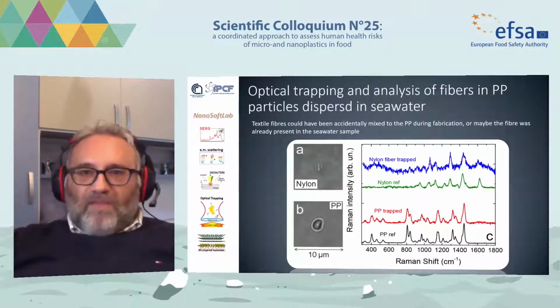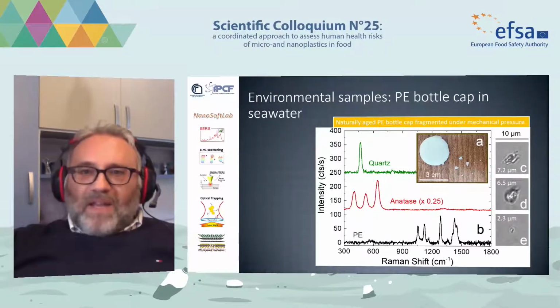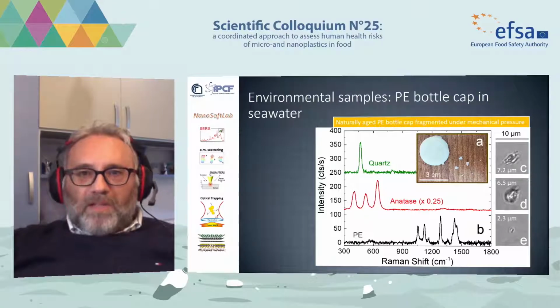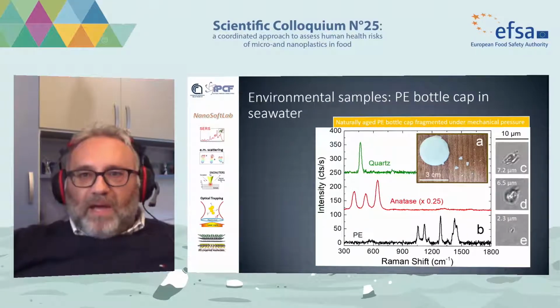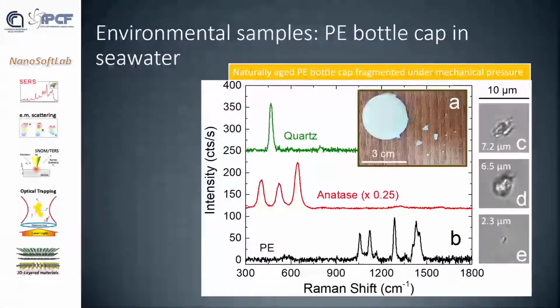Finally, let me show 2 environmental samples. One is a cap of a bottle that was found abandoned for years along the lakes of Ganziri. We discovered it was very brittle, so if we fragment it in water, we can have particles in the micron scale. From the Raman spectra, we can distinguish the polyethylene, the material of the cap, from other particles like anatase, due for example to the earth in which we found the cap.